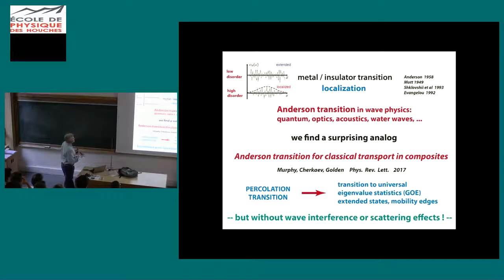So the basic picture there is you have low disorder, extended wave functions for electrons, and then eigen energy levels that communicate with each other because the electrons are seeing each other. But then you raise the disorder, they become localized, and you go to Poisson distributed energy levels. And that's the picture that we're seeing. As we approach the percolation transition, we see this transition to universal eigenvalue statistics. We see extended states and mobility edges that you see in condensed matter physics. But again, without wave interference.